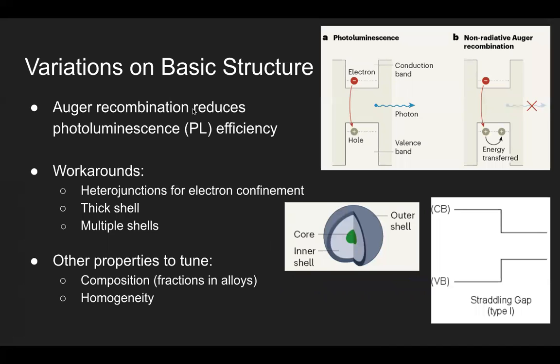Now, we have a basic core-shell structure for a quantum dot, but oftentimes that doesn't suffice for real applications. This is because quantum dots exhibit what's known as Auger recombination. If charge carriers are allowed to go to the surface, then instead of emitting a photon when electrons and holes recombine, as shown here, when they basically come back together, the extra energy is transferred to another charge carrier and thus gets excited instead of a photon being released. This reduces the luminescence efficiency for a photon and for a quantum dot emitting photons. And this does not give us ideal results, especially given that some applications require 100% quantum dot efficiency.